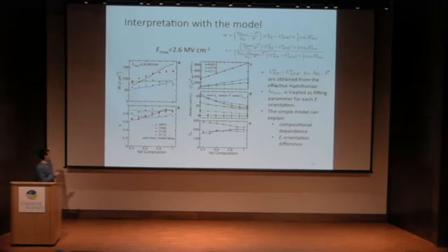So then let's see if we can use the model to explain the compositional dependence. For the 001 field, we have an increasing W versus composition. This is because this delta U is increasing with composition, and this delta EC is decreasing with composition, and delta EC appears in the denominator. This dielectric susceptibility increases slightly with composition. So all these three factors can contribute to the increasing trend.